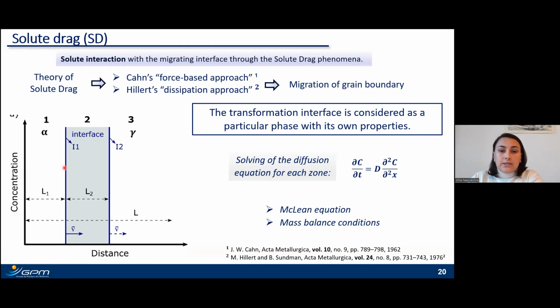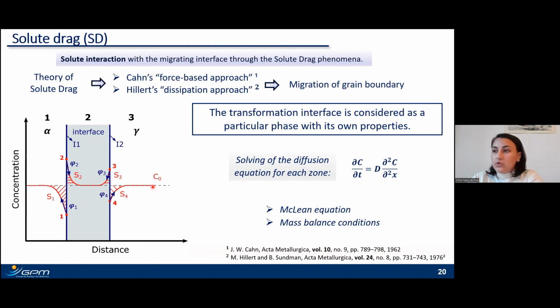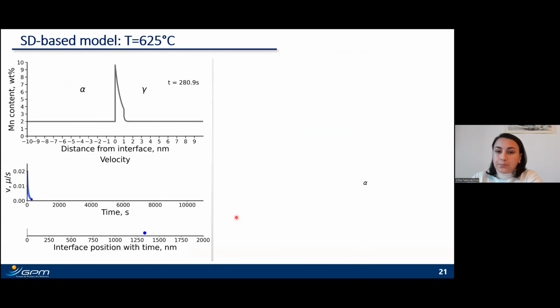Then, to describe the evolution of the compositional profile, the diffusion equation has to be solved for each of these zones: austenite, interface, and ferrite. And to solve this equation, it's necessary to satisfy the McLean equation and the mass balance equation. On the next slide, I would like to show you some results of the calculation using the solute drag-based model at